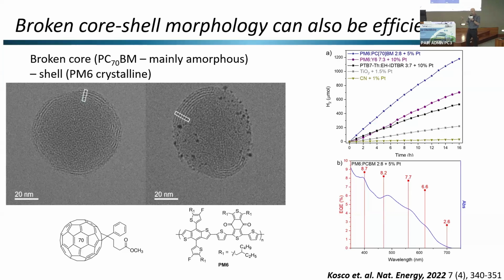So we started to investigate different compositions in order to try to drive the charge generation better. And what we noticed, which kind of surprised us, was that if you have this intermixed morphology, it looks good, but you don't even need that, as long as you have something we call broken core shell.